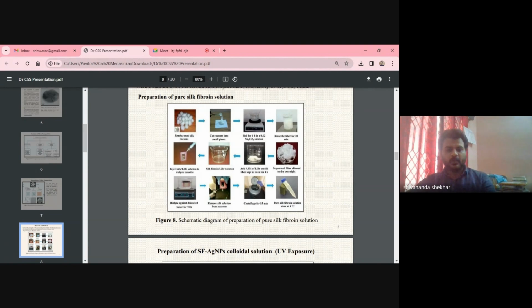Later we take the lithium bromide and fibroin solution and inject it into a dialysis cassette. Here we want to remove the toxic metal ions present in the solution. Because lithium is a very toxic metal ion, in order to remove the lithium ions from the solution, we did the dialysis. The dialysis is carried out for 3 days. Later we remove the solution from the dialysis cassette and centrifuge it. The undissolved silk is segregated at the bottom of the centrifuge tube. So now the pure silk fibroin solution is ready for the next experimental part.